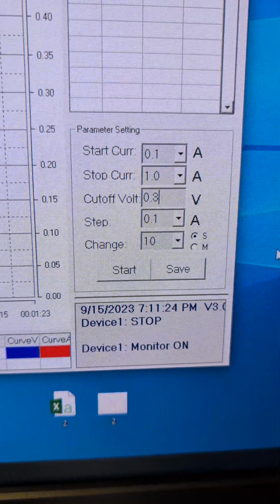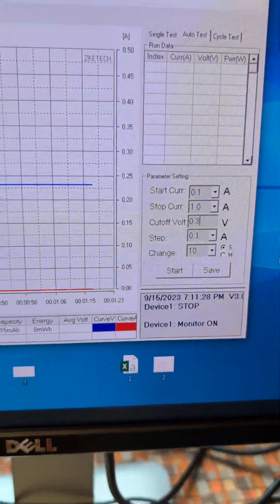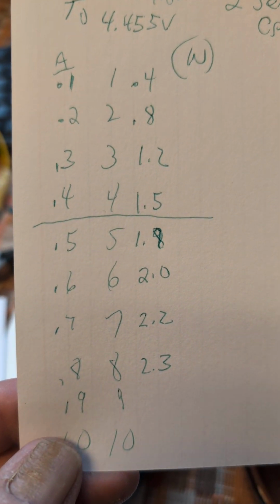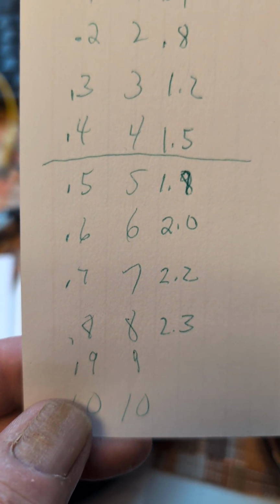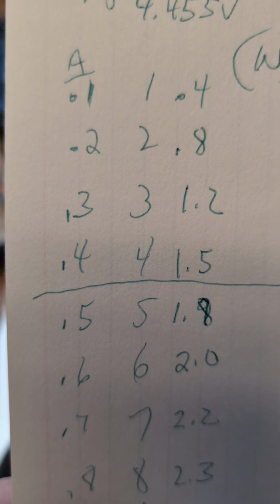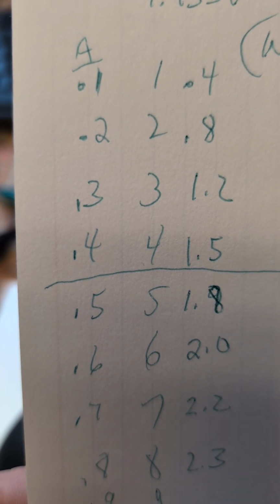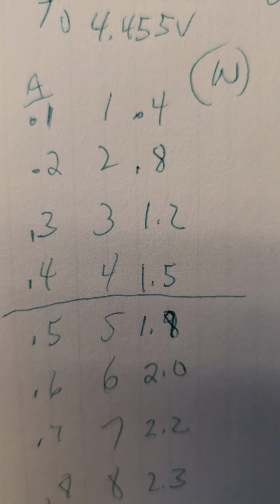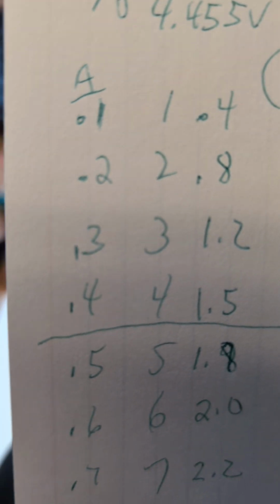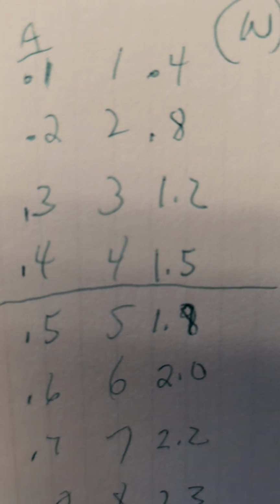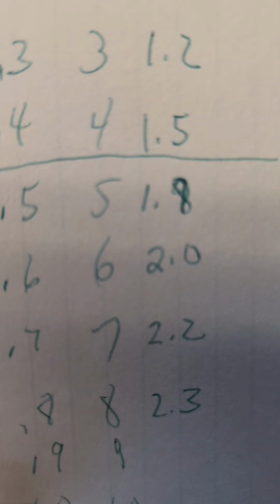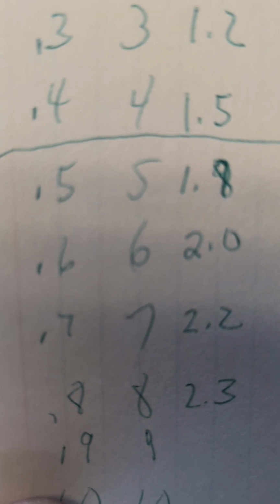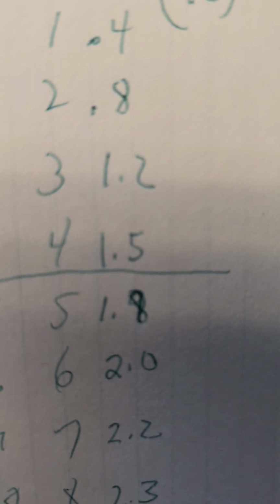It's a good range of variables. Now, what do we see? Anything of interest? Okay, here's some numbers. I happen to write them down for the video. With the 2 supercaps only, here are the first 8 data points. On the left, current. The first one there at the top column, 0.1 amp. And then I have written down the wattage, 0.4 watts. Second step, 0.8. 1.2, 1.5. Notice I put a line there because that's where we're going to see a difference with the graphite in the series. Half an amp, 1.8 watts output.